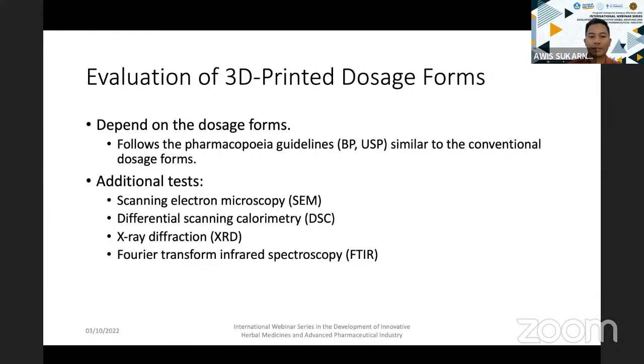And for the XRD, it's almost similar to the DSC. So basically, you want to see if the drug has changed from crystalline to amorphous, or the other way around. Or the other thing with the DSC, I forgot to mention, sometimes we want to see the degradation of the drug as well. So let's say when you combine after the HME, you may accidentally degrade your drug because you're applying too high a temperature. So that's the other point of the DSC.